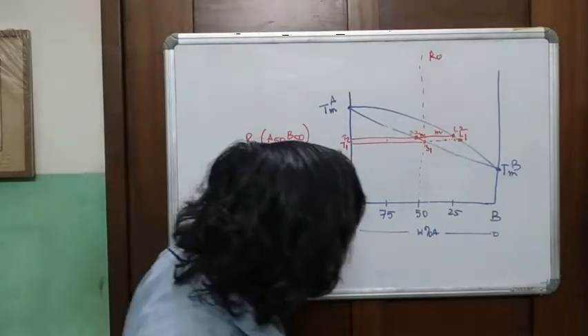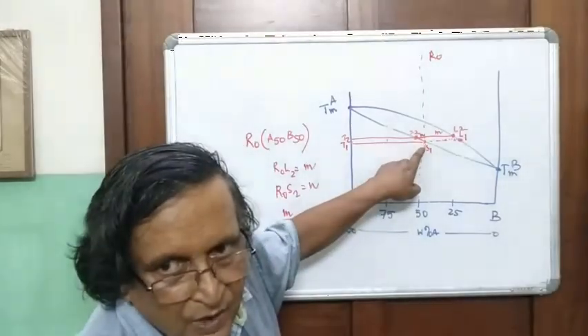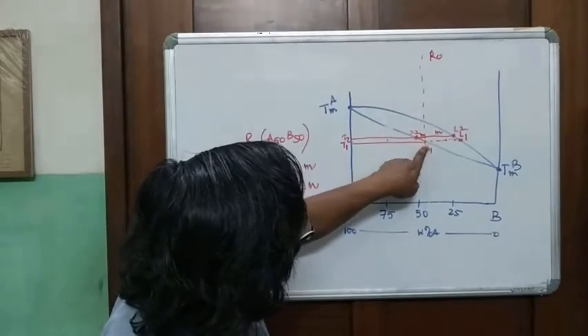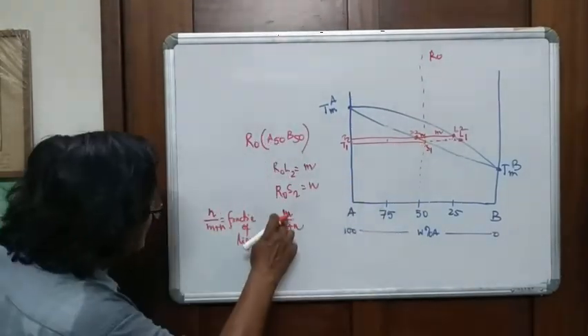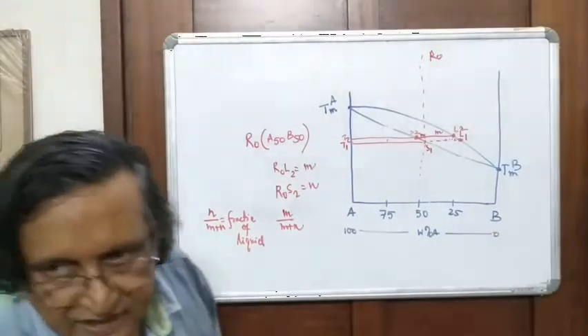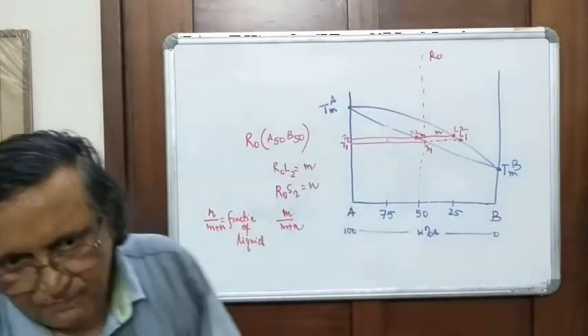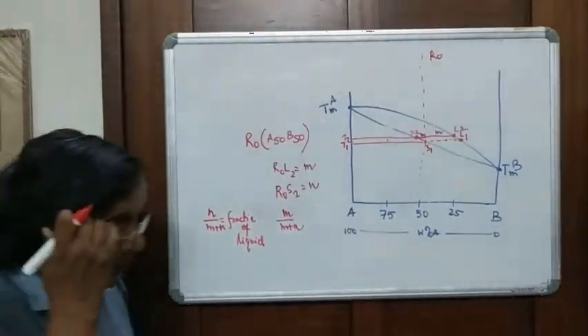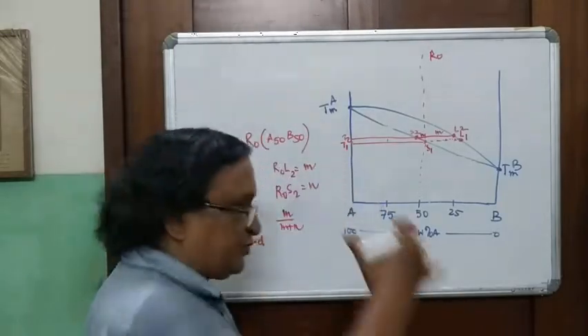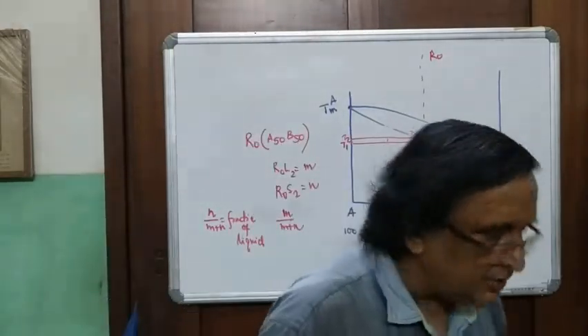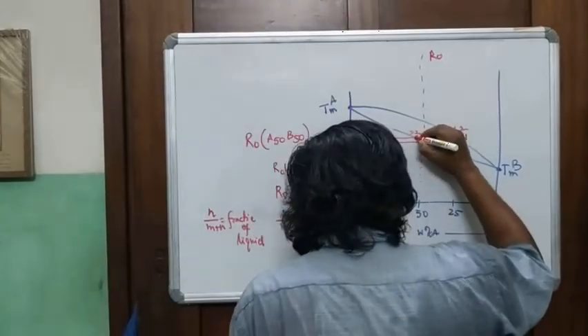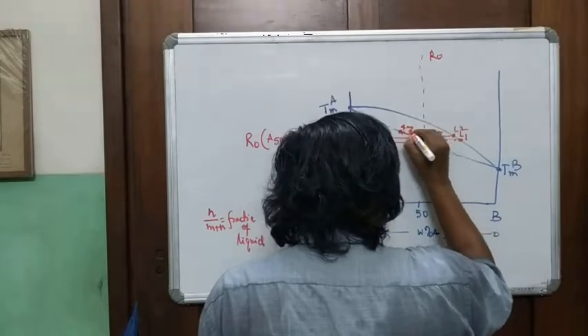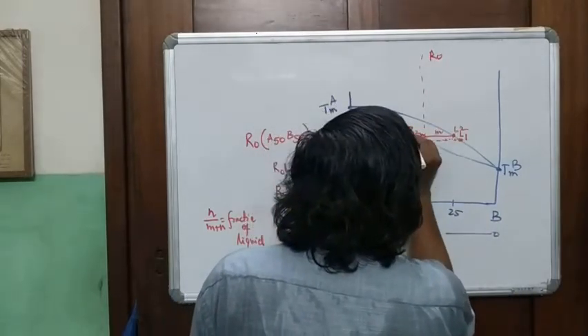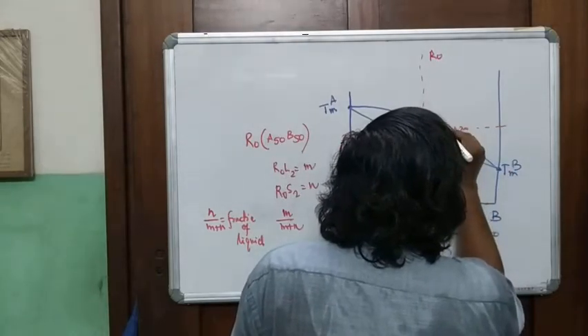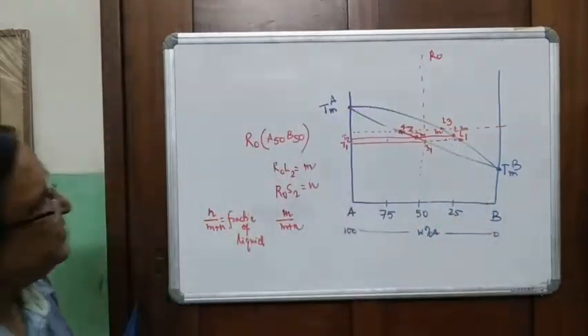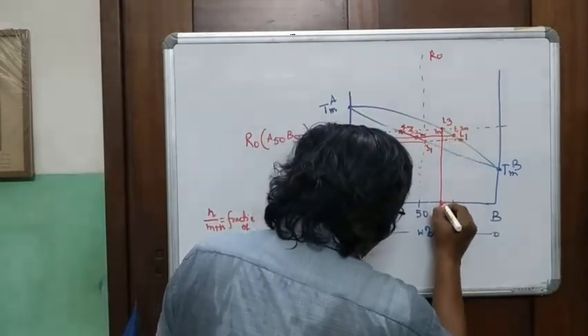Now you see, at T1, at S1, N was 0. That means the fraction of liquid was 0, obviously, because there was hardly any melt when the first melt was generated. So this will go on, it is the reverse process of equilibrium crystallization. And as more S goes into melting, you would have S3 here, and you draw an isotherm parallel to this, and you will have at this point L3. And now you see here, this will be the new composition of L3.